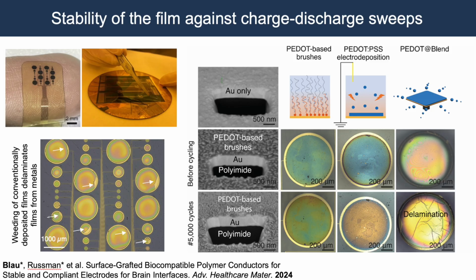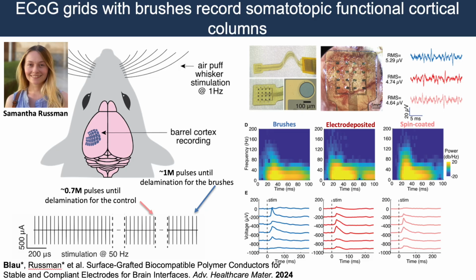And what we found is that by chemically bonding this electronic material directly to the, in this case, gold surface, we're actually able to keep it mechanically compliant for much longer, to the point where we were able to put these electrodes on the surfaces of rat cortices. So this is called the whisker barrel cortex, in order to measure the response of the rat cortex to puffs of air being administered to its whiskers.